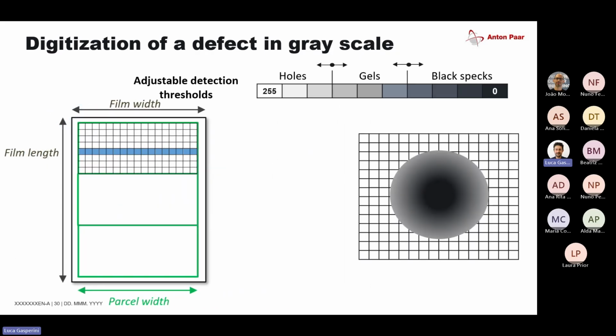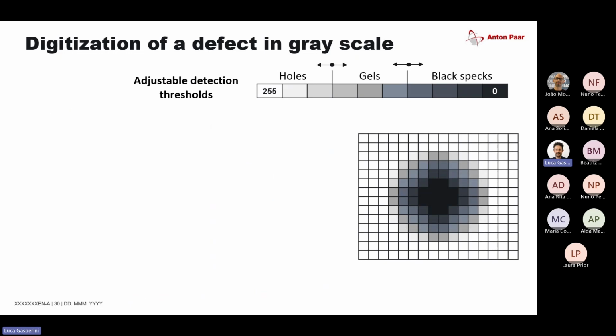So the camera has a resolution. The scan width is around 10 centimeters, and along the line scan, it's roughly around 4,000 pixels. So we get a lateral resolution of around 25 micrometers. Any defect smaller, you wouldn't be able to see anyway with your eyes. So for these applications, this one is fine.